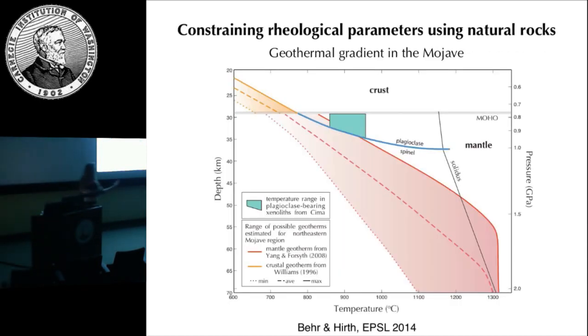And then pressure is a little bit trickier, but fortunately, since we have some plagioclase-bearing peridotites, we can say something about the geothermal gradient here. So for example, we know this plagioclase to spinel reaction boundary in peridotites fairly well. It's basically here. And all of our plagioclase-bearing samples have temperature ranges from about 850 to about 960 or so. So that's this green box. And that overlaps. We also have independent constraints on the geotherm within ranges here from both seismic attenuation data from Yang and Forsyth, as well as crustal heat flow from a paper by Williams and others. And so we can see that our plagioclase xenoliths, given this constraint on the plagioclase spinel boundary, only overlap with the hottest geotherm for both the crust and the mantle.